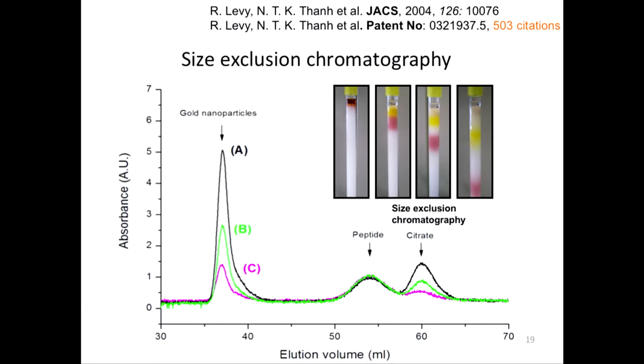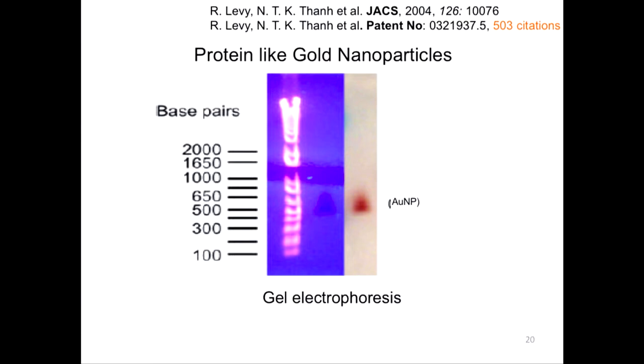Then we can also use size exclusion chromatography to separate them. So you can separate the pure gold nanoparticle without excess peptide or citrate, and now the gold nanoparticles are stable like instant coffee. So you can keep them for years and disperse them in water again. Because they have the peptide surrounding the gold nanoparticles, they behave protein-like. So when you do gel electrophoresis, you can run this protein or peptide-coated gold nanoparticle. They act like a protein.